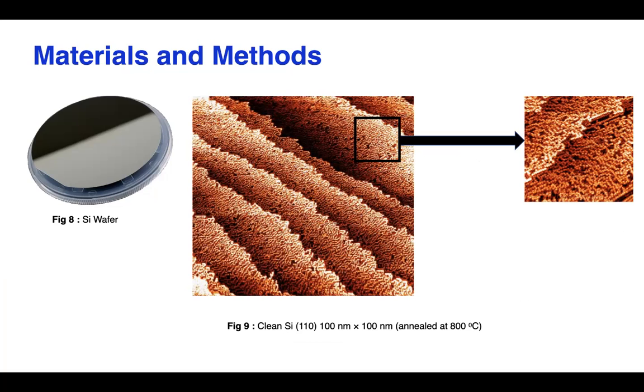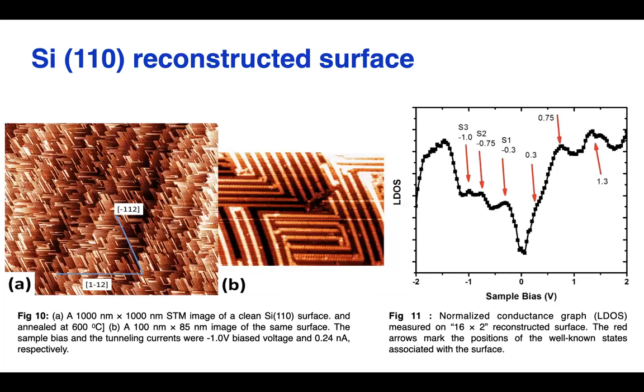So just after flash annealing, I annealed the surface to get the reconstructed surface. We have to follow up with post annealing. In this image, I annealed the sample at 800 degrees Celsius, because this silicon 110 surface is extremely sensitive to temperature. So we have to hit the correct temperature to get the reconstructed structure. In this figure, you can see the reconstructed silicon 110 surface.